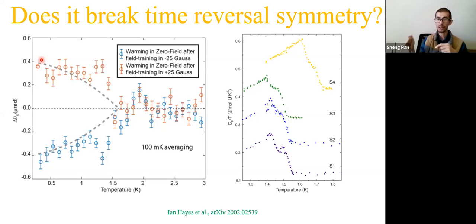But what they did is apply a magnetic field while they cooled the sample down to train the domains, basically to align all the time reversal symmetry domains along the same direction. When you get to the base temperature, they turn the field off, and then they start to do the measurement. So when they do the measurement, there is no magnetic field. They use the magnetic field to align the domains in one direction before the measurement. Depending on which direction you apply the magnetic field for this training field, you can get different sizes of the Kerr shift.